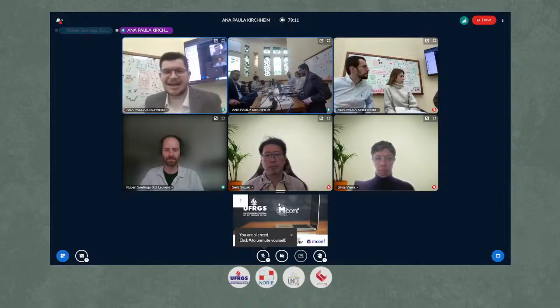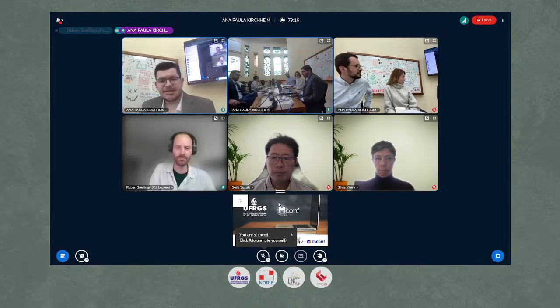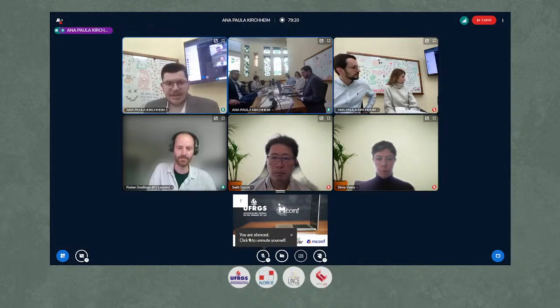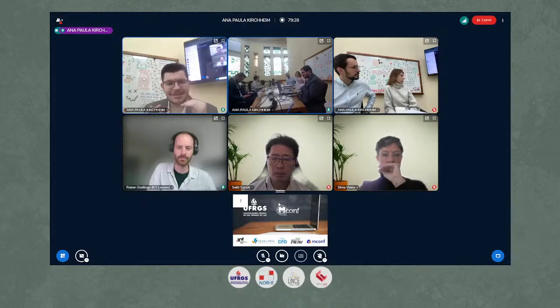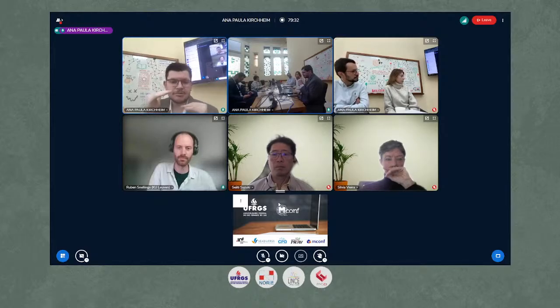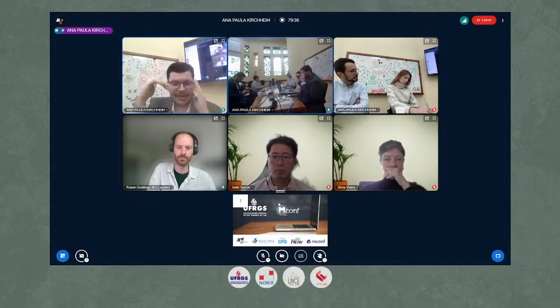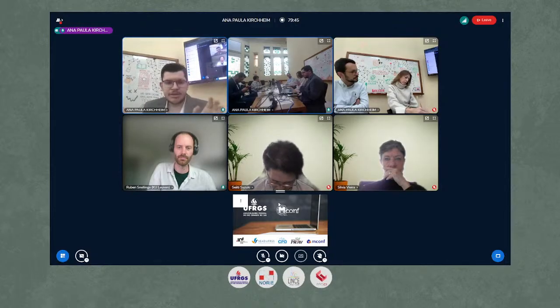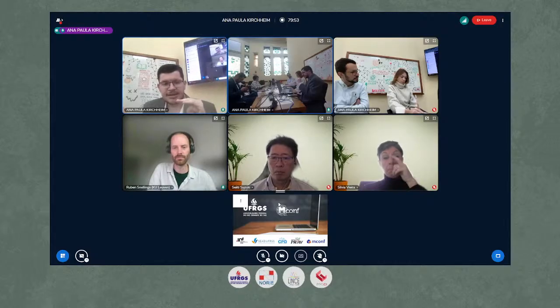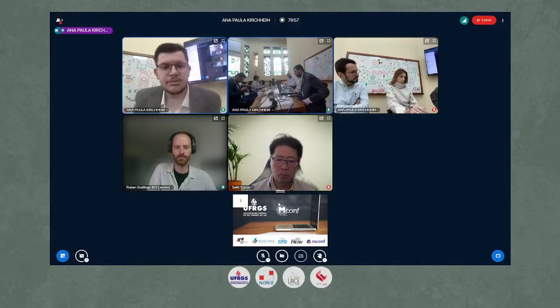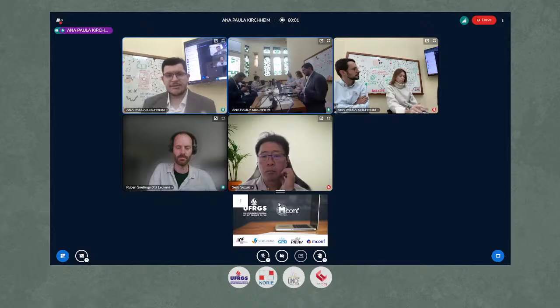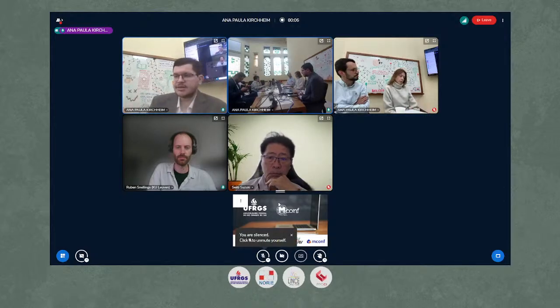Enlighten me there. Yes, this is also a very interesting topic. I observed that usually the optimal sulfate in European clinkers, papers, and so on was lower than the Brazilian ones. Here it is usual to have clinkers with optimum sulfate of 4.3, 4.4, even 4.5, which is the standard limit in Brazil. So I started to think that maybe it's due to the sulfate coming from the clinker. If you compare, in Argentina they have less sulfate in clinker because they use natural gas as fuel. Here in Brazil, we use a lot of petroleum coke with a high sulfur content, so our clinkers have a lot of sulfur in them. And the limit here is 4.5.